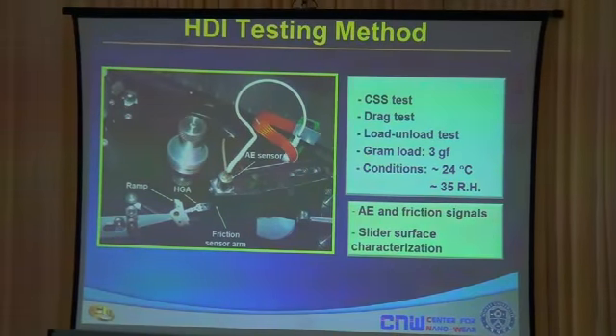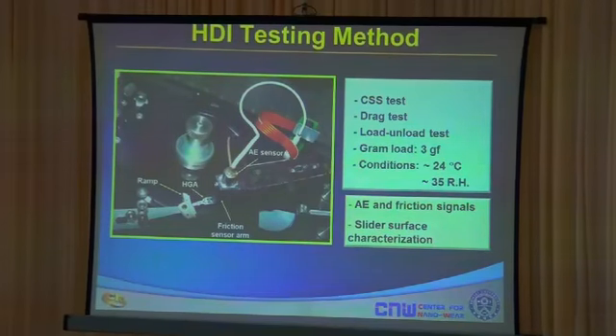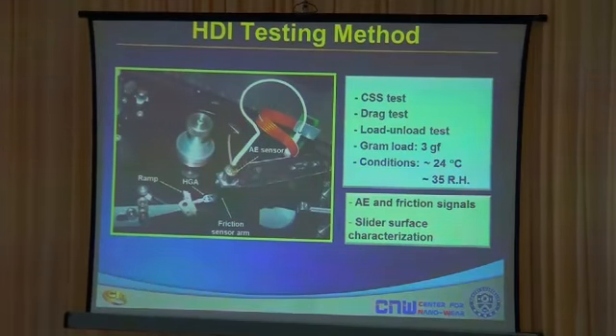And we conduct this experiment in what we call a contact start-stop test. We start it, stop it, start it, stop it. We repeat this for 20,000 times. We can also do this test under a drag test, in which we make contact between the two specimens and run a sliding test at low RPM so the slider will not fly above the disc. And these are the conditions at which we perform the experiments. And we have an acoustic emission sensor to monitor any abnormal signal between the slider and the disc. And also we have friction sensors to monitor the frictional force.